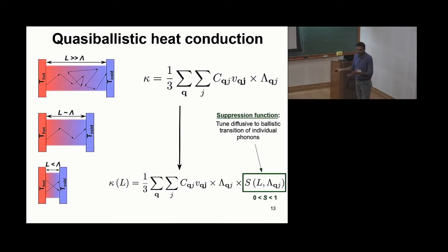So it's a special case of the Boltzmann equation, where S independent of lambda is equal to 1. So you are considering, after suppression, whatever is below L, a gas of those phonons? No, we consider all phonons. If a phonon's contribution goes to 0 because of the suppression, it automatically disappears out of the sum.